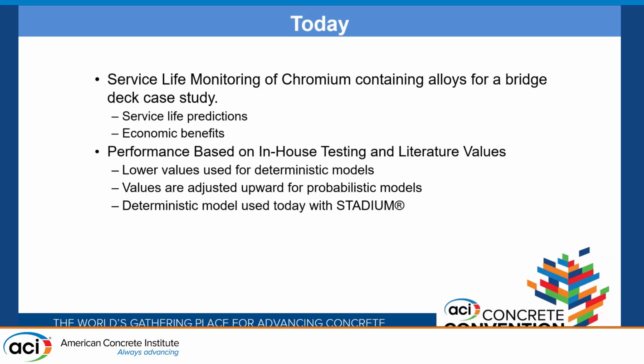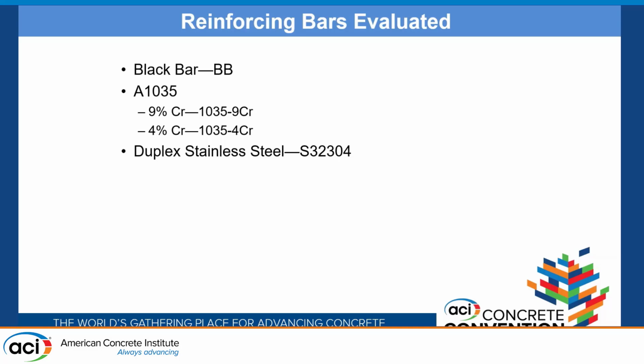If people were here in Boston last fall, we had a session comparing the various models. If you use the models right and you get the right parameters, they all work. But today I'm just going to concentrate on Stadium. So what we're looking at is a black bar, which is this normal carbon steel, ASTM A1035 9% chrome, and another one that's 4% chrome. And the duplex stainless steel in this case was 2304 for this modeling. But you can put anything you want in there once you know the values of what they do, how they behave.